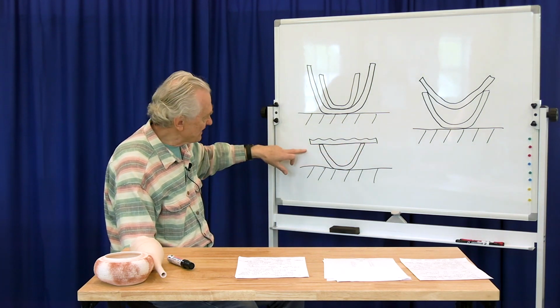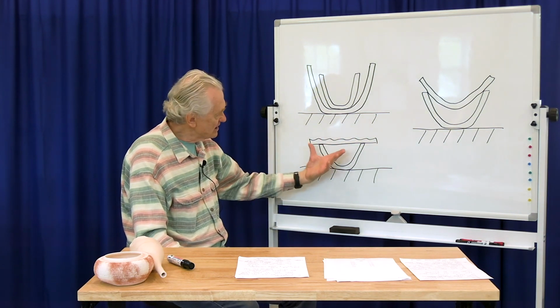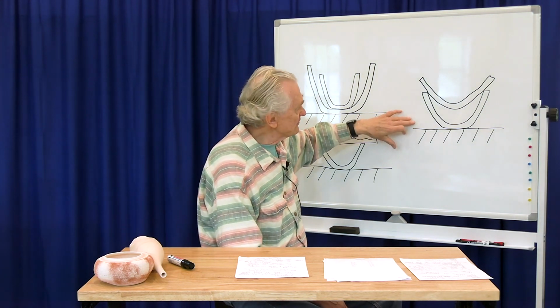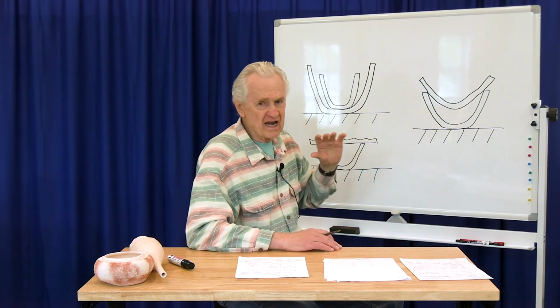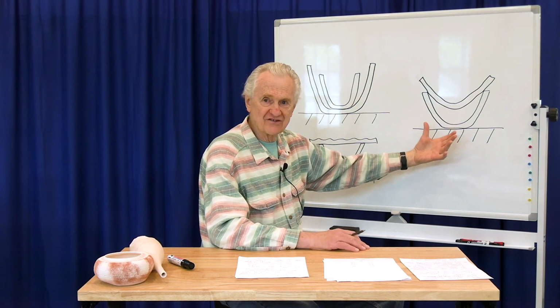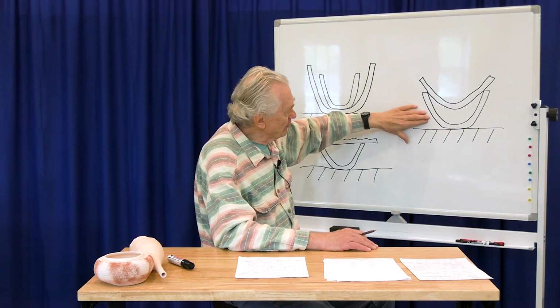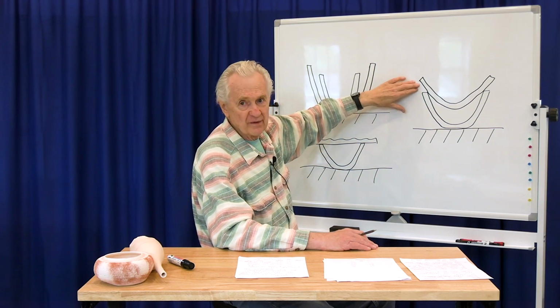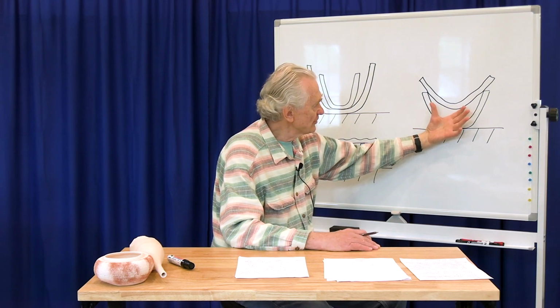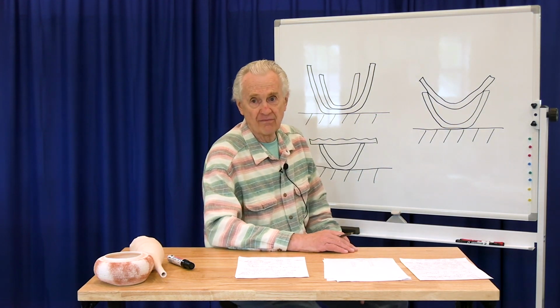You can also do this. You could put something completely flat across the rim because, again, this slab is free to shrink slightly. The rim of this lower bowl is free to move a little bit. This, however, is not a good arrangement. The problem here is there's no guarantee that even if they're made out of the same clay, two pots in the same firing are going to shrink exactly the same amount. So the problem with this arrangement is that the rim of the lower bowl is being restrained by the upper bowl. If the lower bowl doesn't shrink quite as much or wants to shrink more than the upper bowl, it can't. And so typically then I'd get a rim crack.